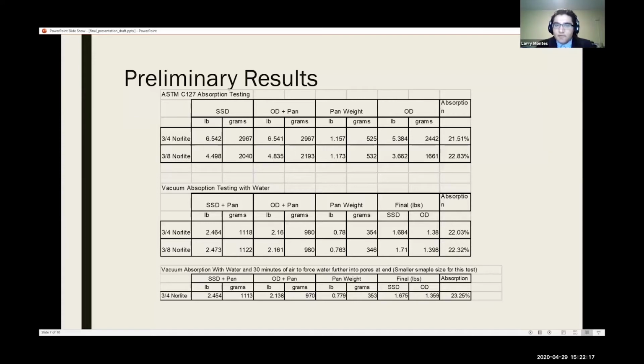So the first test we ran was for the soaking method for the 3/4 inch Norlite and 3/8 inch Norlite aggregate shown above. The measurements resulted in the aggregates having an absorption of around 22%, which means it was able to absorb 22% of its weight worth of water. And then the second test was using the vacuum method, which also ended up with around 22% absorption, which matches the results from other papers we read saying that when the absorption is beneath 30%, you will see both methods